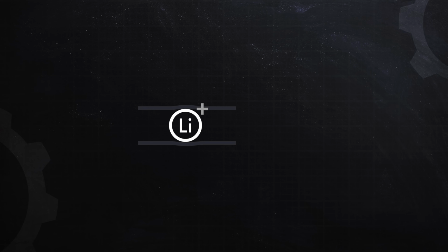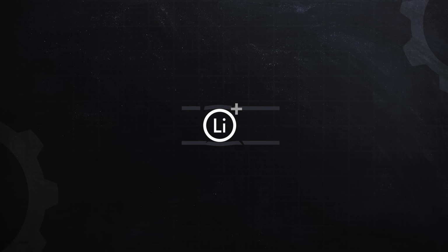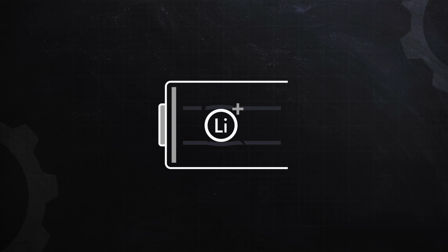As the battery is cycled, the cathode material or structure can also be damaged. This damage is due to the motion of lithium ions entering and leaving the cathode. I like to think of the cathode as two sheets of metal, with the lithium being like marbles that are repeatedly forced between the sheets. Over time, this repeated mechanical stress can lead to cracking of the sheets. And once the cathode begins to crack, some regions become electrically isolated. And this prevents electrons and lithium ions in the isolated region from migrating back to the anode during charging.